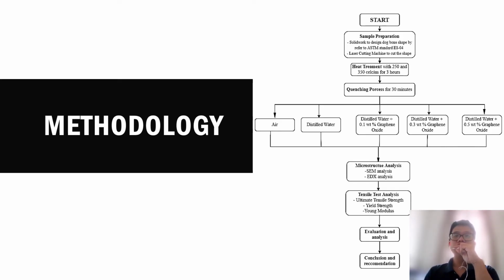Next is methodology. This is the flow of the experiment on magnesium alloy AZ31B. First, SolidWorks will be used to draw the dog bone shape. Then the laser cutting machine will cut the dog bone shape from the raw material of AZ31B. After that, the AZ31B will undergo the heat treatment process at 250 and 350 degrees Celsius for 3 hours. After the heat treatment process, it will undergo the quenching process for 30 minutes. The mediums used in the quenching process are: distilled water, distilled water plus 0.1 weight% of graphene oxide, distilled water plus 0.3 weight% of graphene oxide, and distilled water plus 0.5 weight% of graphene oxide.